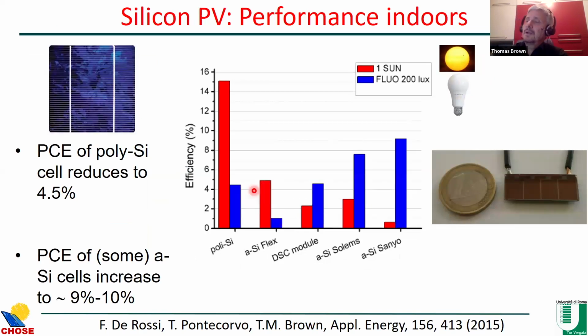Well, we then measured them under a fluorescent lamp at 200 lux, which is the residential area typical lighting conditions. And you can see why. So the polycrystalline silicon cell, the efficiency dropped from the 15% under sunlight to around 4% under this lamp. Whereas some of these amorphous silicon devices increased to beyond 8, 9, almost reaching 10%. So, double the efficiency of crystalline silicon indoors. So there's a huge increase.